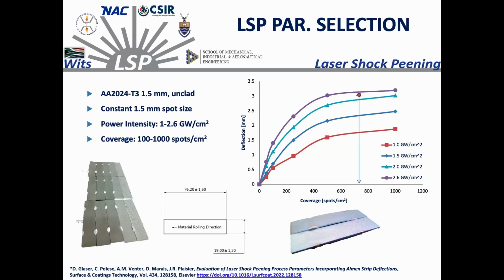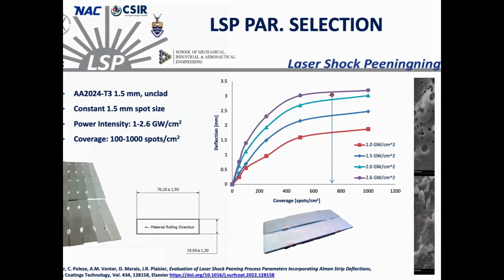The method that we use to select, let's say, promising parameters is based on a method that we outlined together with Dr. Glaser, that is basically a modified Almen strip approach for shock peening, very similar to what you have for normal shock peening. We're trying to see at which set of parameters we have an effective response of the material in terms of deformation. Beyond a certain point, we reach what we can call a saturation effect. So from the industrial point of view, it doesn't make sense going beyond that, because we don't see many changes in the material.